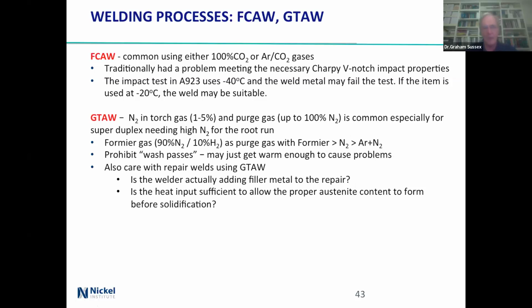And if you're doing repair welds, do you actually get the filler metal to the repair? And it's low heat, so have you actually got enough heat in to get proper austenite content to form before solidification? Because remember, it solidifies as ferrite, and then it has to cool slowly enough below 1,000 so that you actually form the austenite.